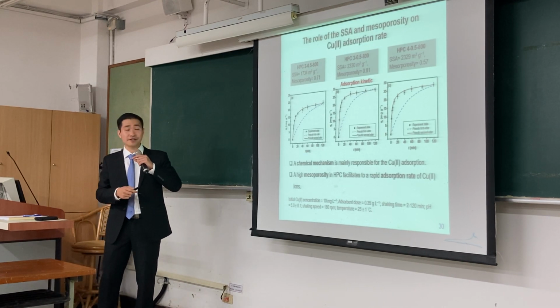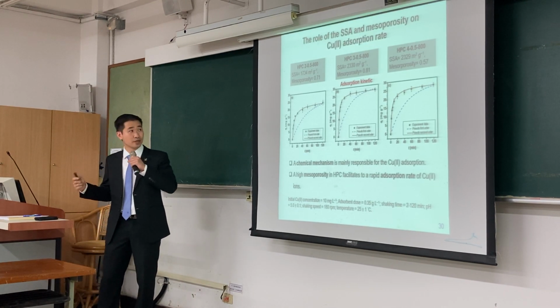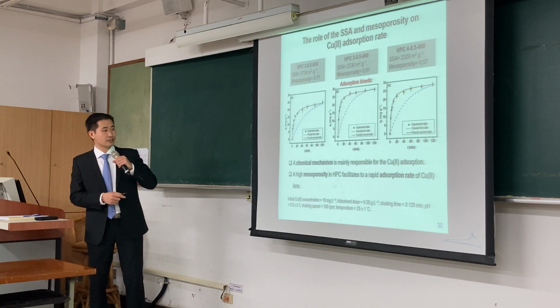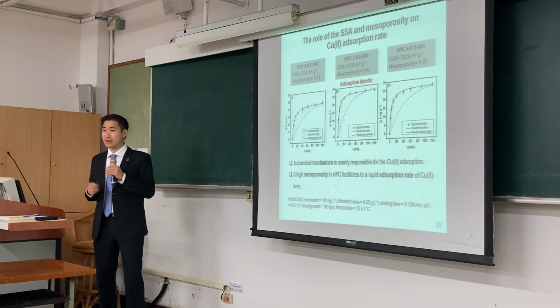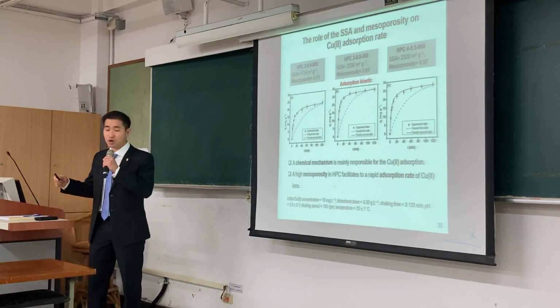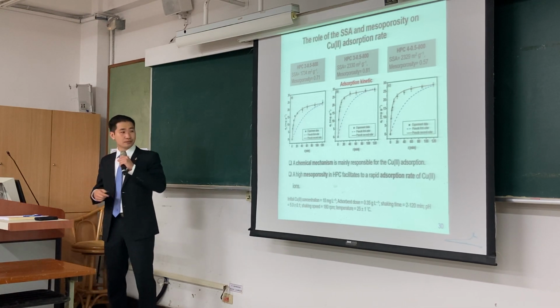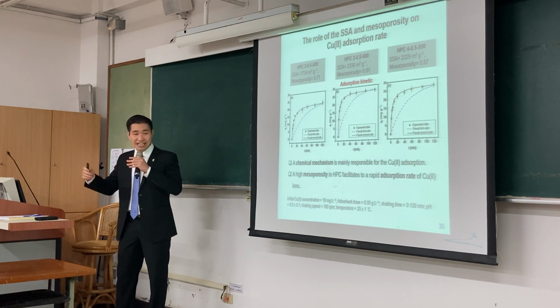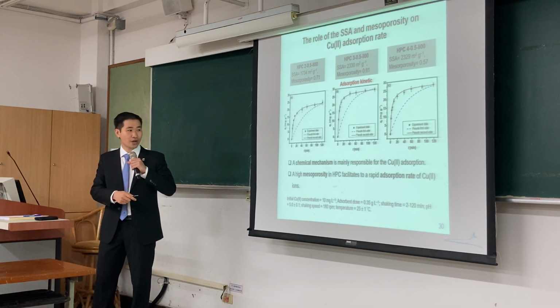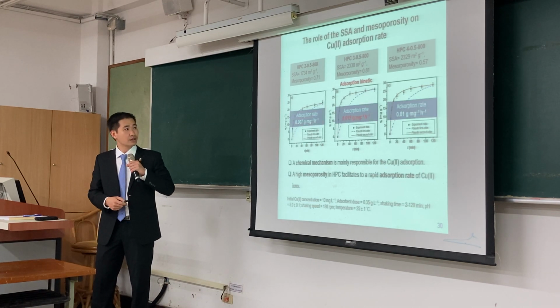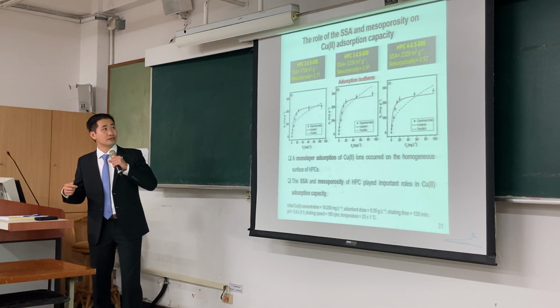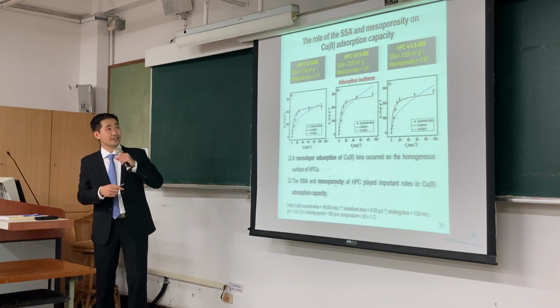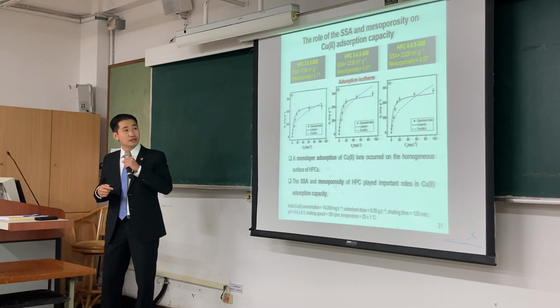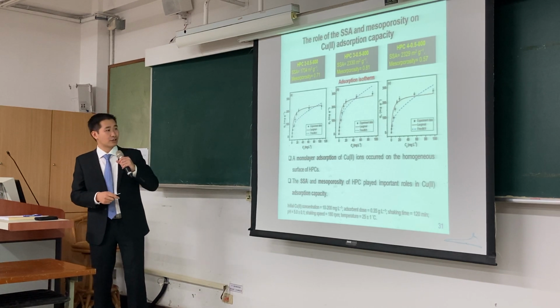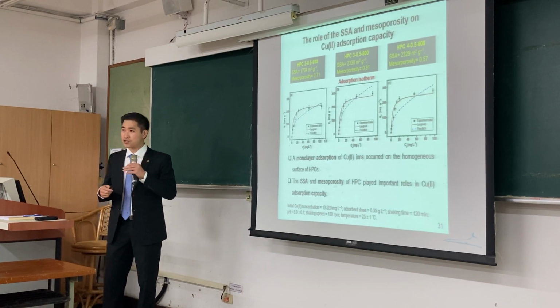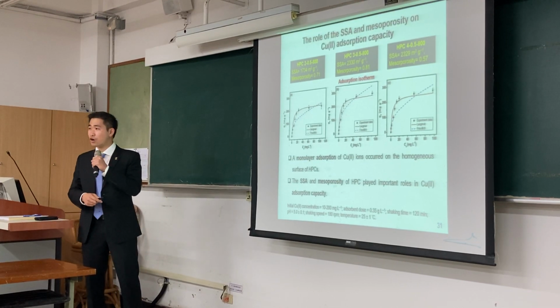The role of specific surface area and mesoporosity on copper adsorption rate is investigated. The results show that a chemical mechanism is mainly responsible for the copper adsorption, and a high mesoporosity of HPC facilitated a rapid rate of copper ion adsorption. Moreover, the role of specific surface area and mesopores was investigated for the adsorption capacity. We also see that monolayer adsorption of copper ions occurs on a homogeneous surface.